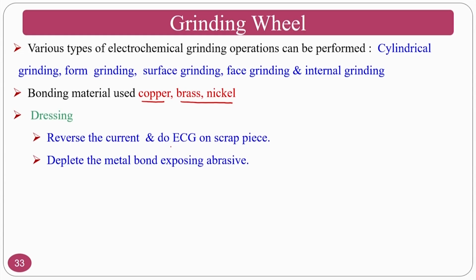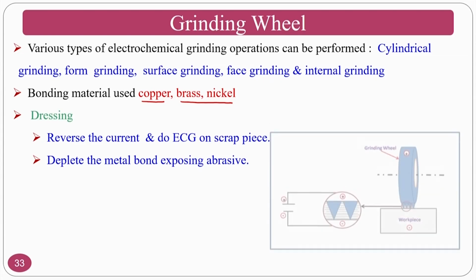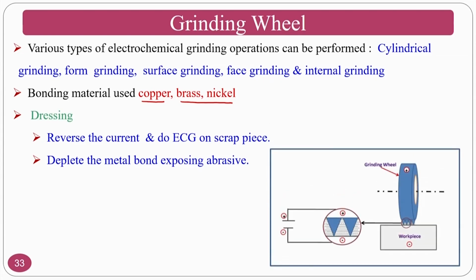If you do the ECG process, then the material that is loaded between the abrasive grains can be depleted, or it can dissolve and go off along with the electrolyte. You can see here the dressing can be done automatically by changing the polarity, and if you perform that, the material that is loaded is dressed.